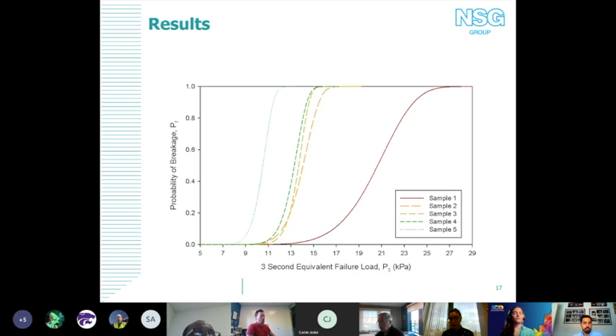Once we applied the frit onto the glass, everything other than the control sample had frit on it, and the coefficient of variation significantly reduced. So it's probably the same reason for mechanical failure that we're seeing in our previous tests. And again, at this mean level, there's not really a clear correlation with regard to what your percent coverage is. It wasn't like 40% reduced it this amount, 50% reduced it a little more, 60% a little bit more. There was no clear answer or solution to show how that worked. But what we saw was significant load resistance reduction in general. So next slide.